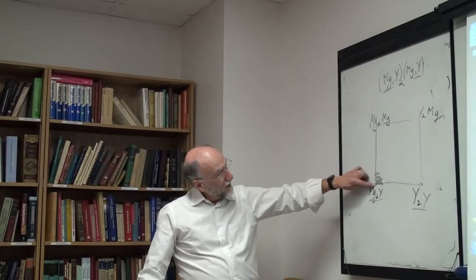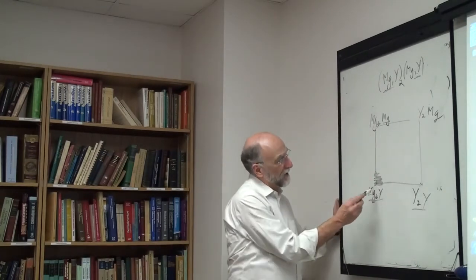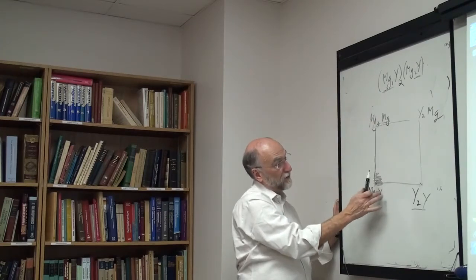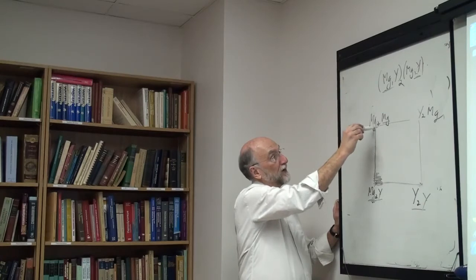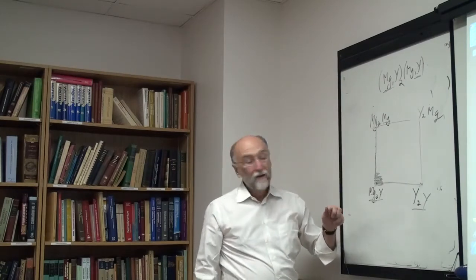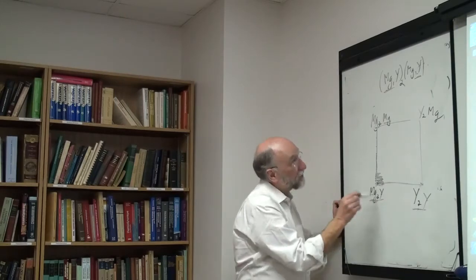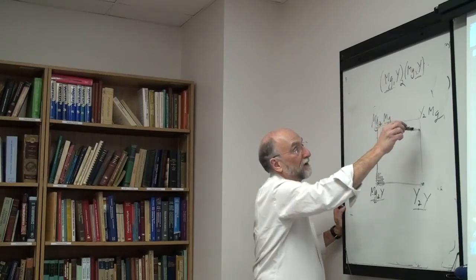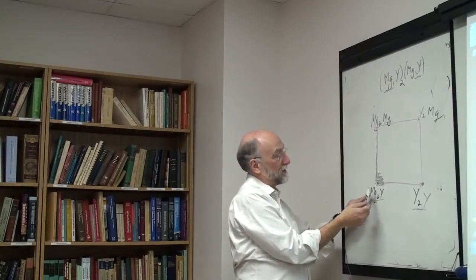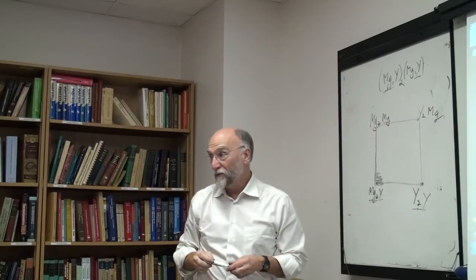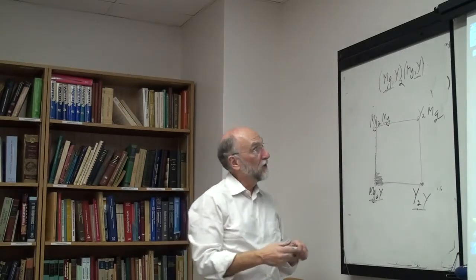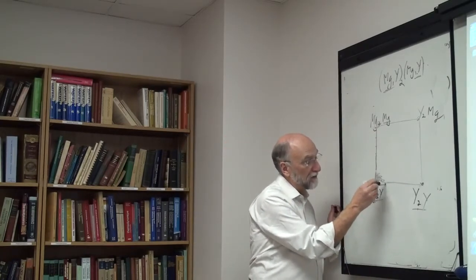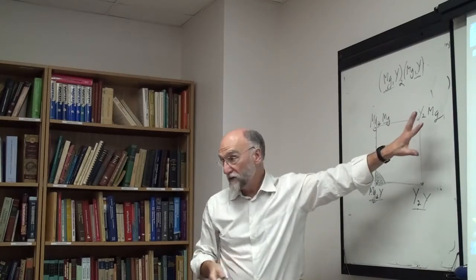So I'm starting here with Mg2Y. This is where all my real solution is. If I move along this range here, I'm replacing some of the yttriums by magnesium as a substitutional disorder. And this is just hypothetically, if you go all the way, you get Mg2Mg. Here I'm replacing some of the magnesium by yttrium on this sublattice. If you went all the way, you'd end up with this hypothetical end member. And over here, I've replaced everything on this sublattice and everything on this sublattice, so this is really very hypothetical. So I'm in this reciprocal solution with 2 sublattices, but my actual main composition is only over in this region. The rest of it is kind of hypothetical.